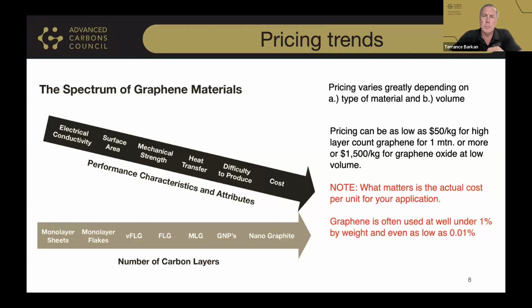And so ultimately what people need to look at is not the cost on a per unit basis for the graphene, but what does it cost to put graphene into your system to get an improved level of tensile or flexural or impact resistance in terms of strength for the component that you're adding it to. And you could have two different types of graphene, one of which you might be using 1/10 of the other. And therefore, you have a tremendous impact on what your actual end use cost is as used. Where we're at today with graphene, it is a very cost-effective additive to be used in composites and can be less than some of the resin systems in terms of cost and what it can replace.